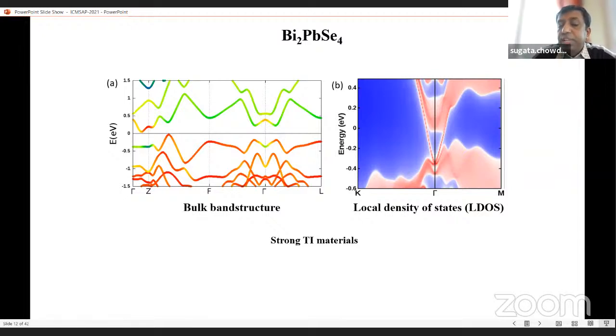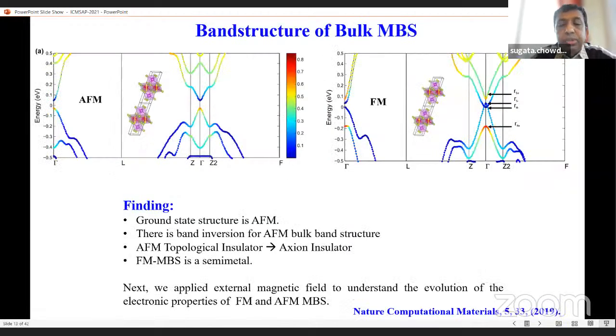So we first focused on that material, and then I was saying, okay, if we replace the lead by manganese, what will happen? As we know, any kind of material that is magnetic has two possibilities, ferromagnetic and antiferromagnetic. When we found its ground state, it showed that the manganese-based selenide structure is actually an antiferromagnetic ground state. That means we can apply an external magnetic field and modify the property of the system.